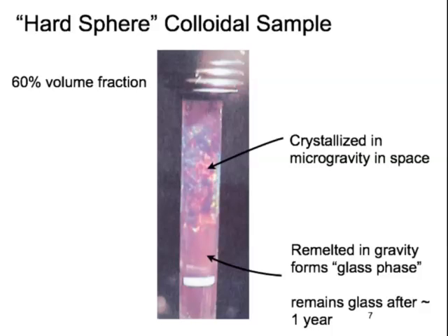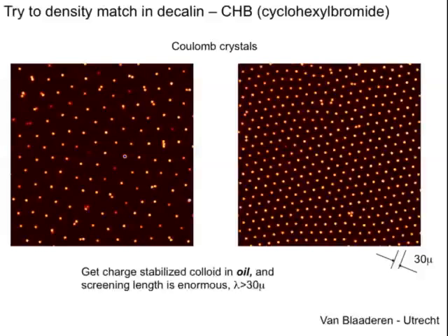So a lot of groups tried this, and what they ended up with is, for instance, something that looks like this. These are 1 micron spheres, PMMA spheres again, and they form a nice crystal like this, but the spacing between them is 30 microns. So they're nowhere near touching one another. So what happened is, in adding this other component, they no longer had hard spheres, they had charged spheres. And the Coulomb repulsion between them was giving you this Wigner crystal over here. This is a 3D Wigner crystal. Okay? Here's another one over here.